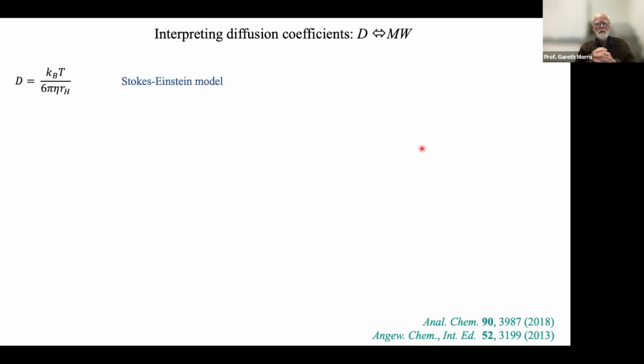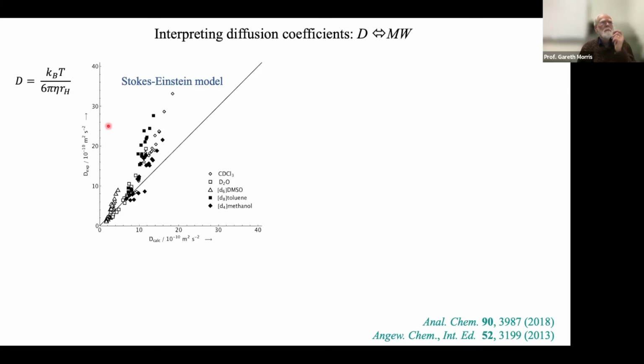The rate at which our ball diffuses through solution depends on two things: thermal energy kicking it along and viscous drag holding it back. And so we have a balance between thermal energy and viscosity, and the balance is mediated by the hydrodynamic radius, how big our species is. And so suppose we take the approximation that all molecules are made of green cheese, so they all have the same density, then we should be able to rationalize diffusion coefficients. So if we take that approximation, we choose a suitable density for all molecules, then disappointingly, what we see is that our ability to correct diffusion coefficients is better for low diffusion, big molecules, and it's better for small solvent